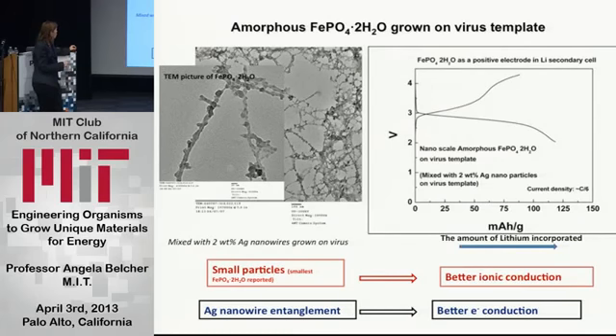But one of the ones they started with was iron phosphate material. They started with amorphous iron phosphate because it was pretty easy for us to grow biologically. And people had been looking at iron phosphate material, not lithium iron phosphate, but amorphous iron phosphate, but it wasn't proving to be a very good material. And so my students went in and they grew it and nucleated it on the nanoscale and showed they could make these nice particles. And then they used some of the tricks that we learned before, either integrating small particles with silver nanowires, or having one virus with iron phosphate and another one with silver, and mixing them together, and they got better ionic conductivity and a better electrical conductivity by doing these together.